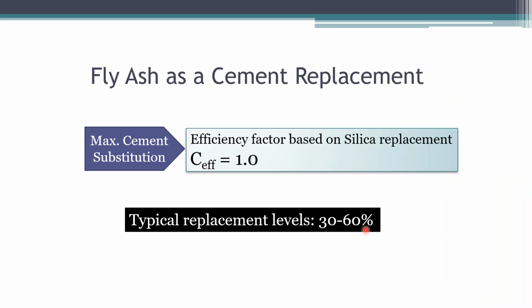So now coming to this particular thing, what we developed is a rational way of replacing cement with fly ash. And we developed what is called an efficiency factor. This comes from thermodynamics. You can actually calculate this. And the whole point is that if I hit an efficiency factor of 1, then I achieve the same performance as what I would get with pure cement or pure clinker-based cement, even on substituting cement with fly ash. Now, if we go by this efficiency factor, I can replace up to 60% of clinker with fly ash and still achieve the same performance. And that is what we've looked at.